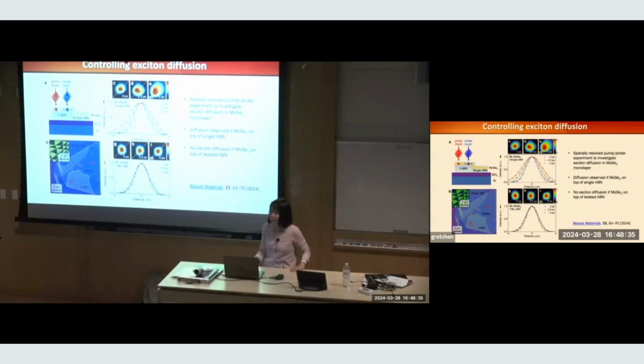You're describing how to actually construct the Moiré heterostructures with a set twist angle. It seemed like once you do that, it's a very final and set property. Are there any ideas about dynamically controlling the twist angle? Certainly, people have. Okay, so it's hard to rotate a single layer against a single layer. That's why I also like the HBN. There are people who learned how to make a wheel, carving out a little driving wheel for the HBN. You can take an AFM and push that wheel. You rotate, you change the size of the supercell. It's pretty cool. So it's possible to do dynamic control.